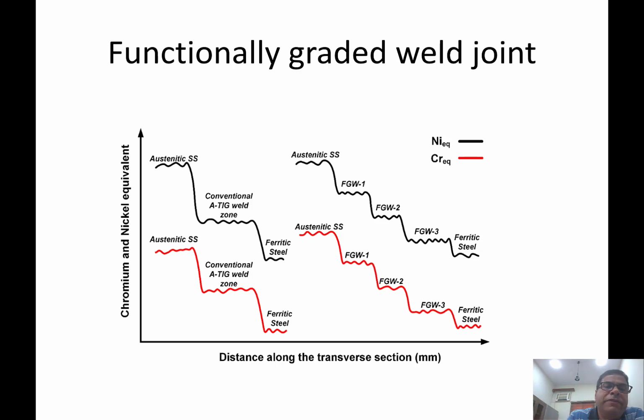Just for an example, if we see austenitic stainless steel welded with ferritic steel, then direct conventional welding, a direct connection between the two metals without any use of filler, leads to a lot of difference in the composition across the two components. Like this side is ferritic steel, this side is austenitic stainless steel, then there is a sharp gradient, a sharp change in the composition in terms of the nickel and chromium equivalents.